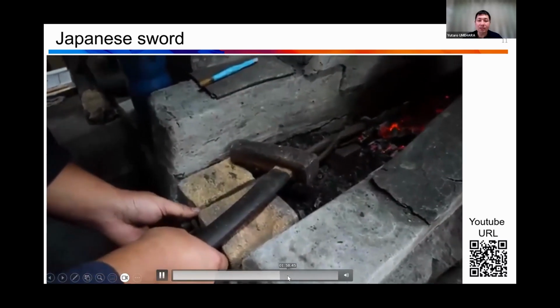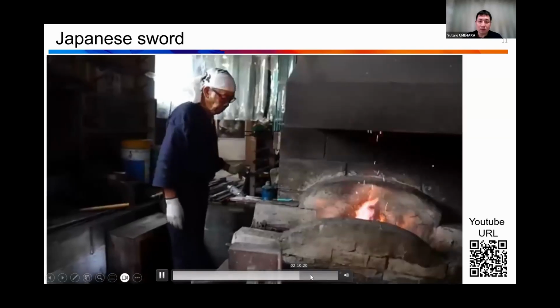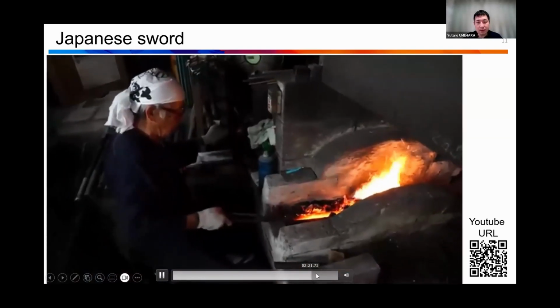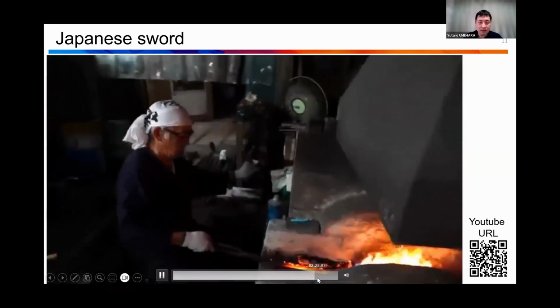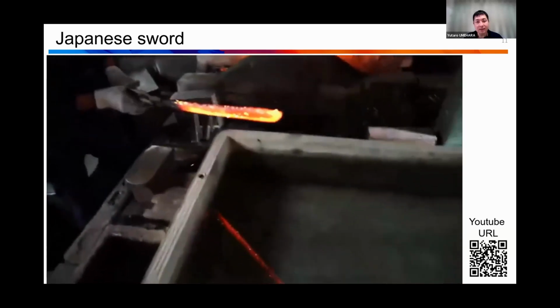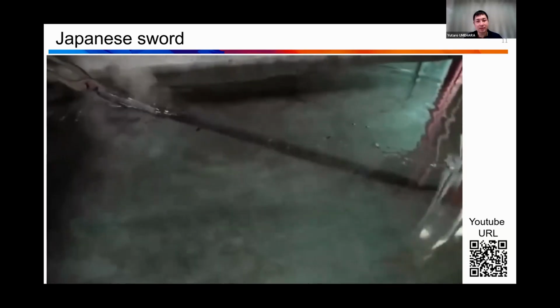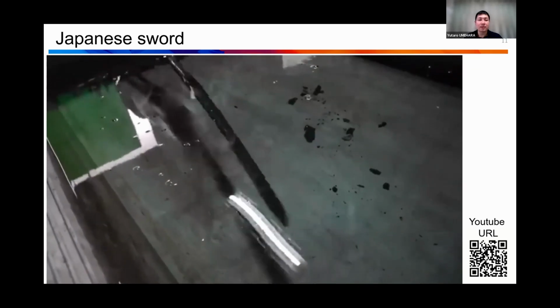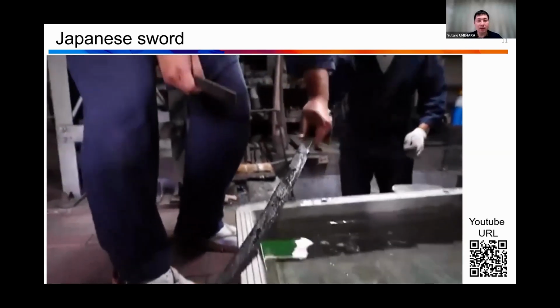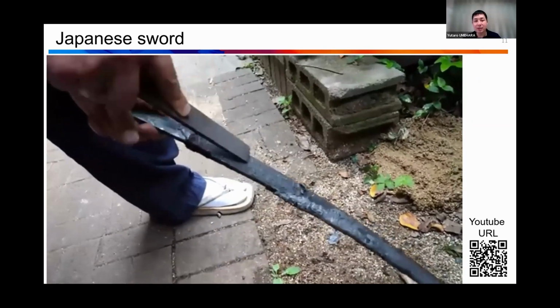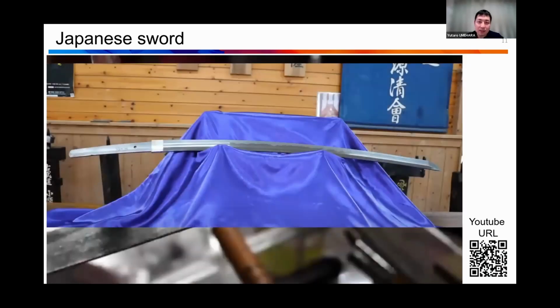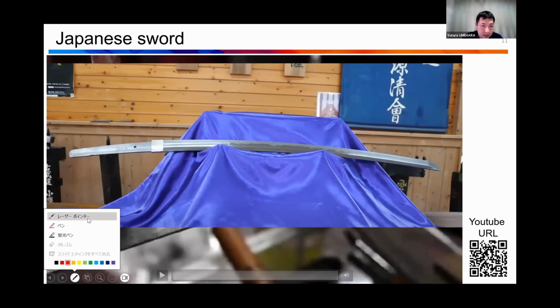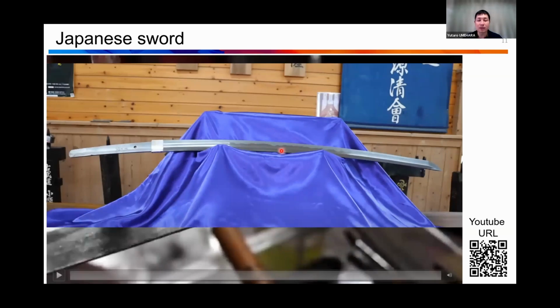After that, they heated up the Japanese sword to 1000 degrees C, and then they quenched it completely in a water bath. So this quenching phenomenon is very important to make a great Japanese sword, and also the pattern on the surface is very important. Some clay pattern is very important to make this pattern on the sword. Okay, so this is quenching phenomena in Japan.